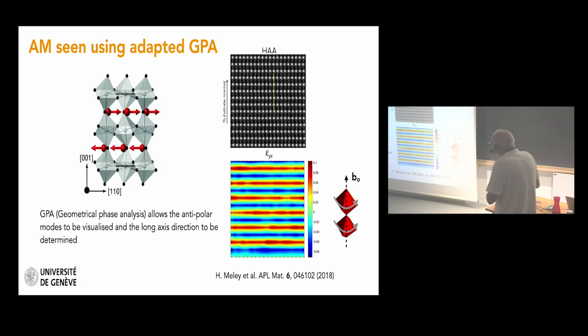antipolar motion. And if you do scanning transmission electron microscopy and you look at the lattice, and if you have good eyes, you can see directly the zigzag of the A cations. But there is a technique which allows this displacement to be observed. It's an adapted geometrical phase analysis, which in general is used to determine strain. But if you use this technique, and this is what you see here, you can beautifully see the displacements. So red and blue indicate displacement of the A cations in different directions. And when you see this, you know that the long axis, the orthorhombic long axis, is perpendicular to this displacement.